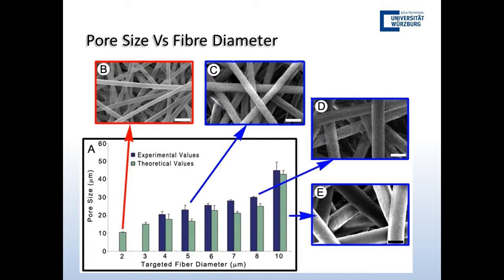However, for people working in electrospinning, this is not good news, because this is not nano anymore. And I've had people say to me, oh, your fibers are 3 microns, that's not interesting because it's not nano. Which is actually kind of crazy, because I'm sure cells don't subscribe to the SI unit system, and they don't decide whether to invade the scaffold because it's not nano. But the important thing is you still have high surface area. You still allow cells to penetrate this time, and they showed this in this instance. We actually see cells penetrate into them, and these are just randomly deposited fibers. And this is a very important paper to talk about.